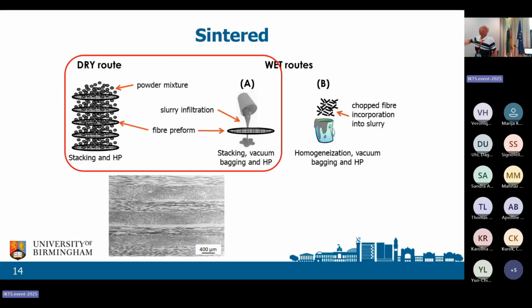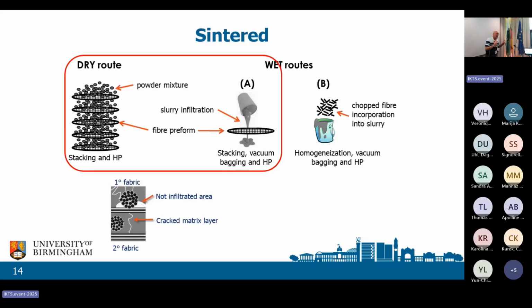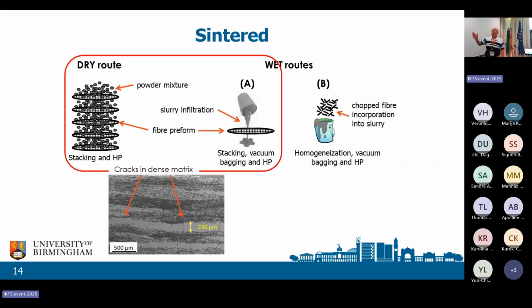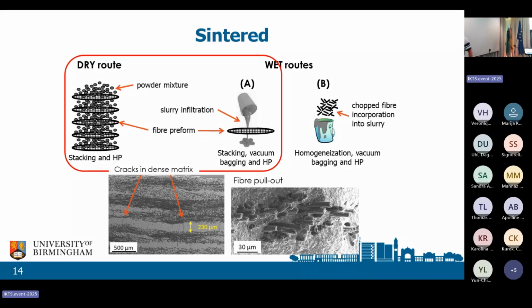Focusing on the continuous fiber, what you will end up with is layers of material and layers of matrix in between them, and the whole thing is hot pressed together. But especially if you do it dry, you will end up with areas that are non-infiltrated and cracks running. Where you've got an area that's perhaps got an agglomerate in it, you can get a cracked matrix running between the two. These things have a microstructure, and you look at it and think, ugh, don't like that microstructure, but actually they do perform. They can perform very well. And the proof of the pudding is pull out. You'll get some pull out. Pull out means toughness. It means improved performance.